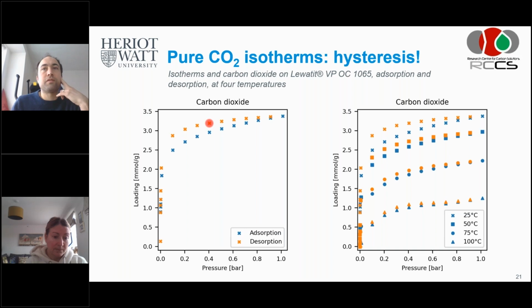If you think of an Arrhenius equation, for instance, where you also have the energy barrier and an exponent. So you simply need more temperature to be able to release the CO2 again. I don't know if this fully answers your question, but this is what we think. That was it. I was explaining that basically when you lower the pressure, the carbon dioxide sticks around, so it doesn't leave. So in that sense, it makes sense to me.